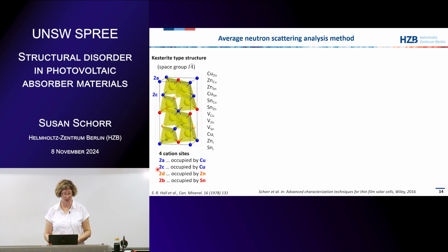And for the kesterite structure we have 2 positions for copper: the 2a position, which are the corners of the unit cell and the middle one, and the 2c position, which is this one and that one, as well as this one and the one which is here behind. Then we have the 2d position, which is occupied by zinc, and the 2b position, which is occupied by tin. And then we have all these defects which could be formed: antisites, vacancies, and interstitials.